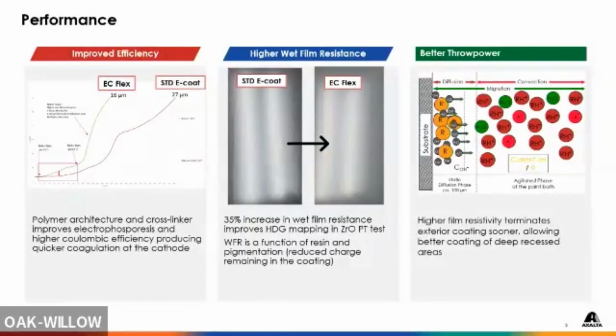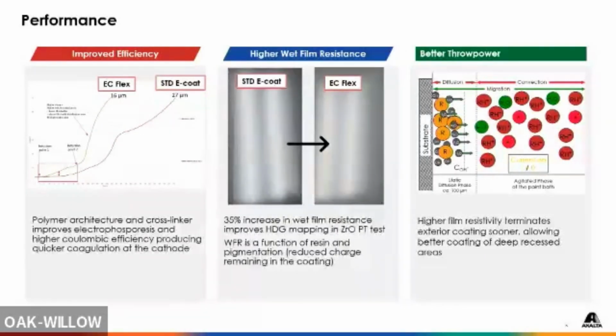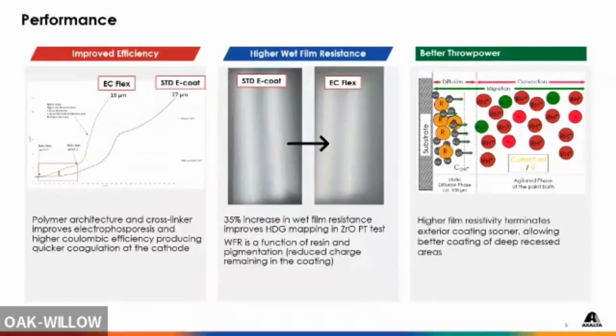The ability for this material to coat out and carry a charge. As you can see, we've improved dramatically our wet film resistance compared to a standard Ecoat. If I look at this graph here, across the bottom is time, and on the left is the film thickness. So as you can see, after that quick induction period, AquaEC Flex has already started coating to the target film build, whereas the standard material is still building.